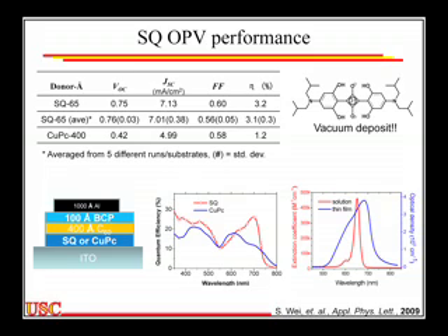And if you look, this is one of the compounds I'm going to spend most of the time talking about. The red curve is the solution spectrum, and the blue curve is the thin film spectrum. So I get a very high extinction, and I also get a very broad line with a high optical density for the thin films. So this has a peak optical density of 4 × 10⁵ per centimeter, which is really high, and a line width of almost 200 nanometers. So it's quite broad, exactly what we want.